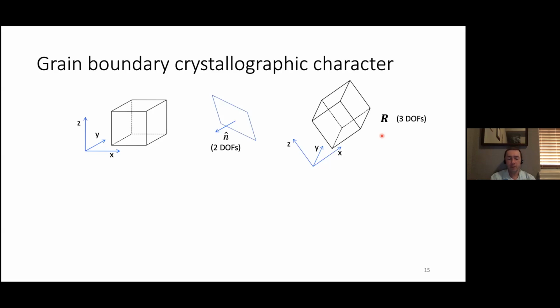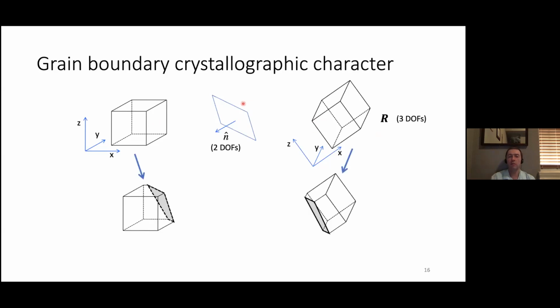Just to finish the thought here, once you have this grain boundary plane orientation, once you have the orientation of the two grains, what you do next is then you imagine cutting each one of those two grains along the boundary plane facet direction. Right, so imagine that I take this plane, I use it to cut this grain, I then cut this grain with the same plane orientation. You get these sort of facets that form, and then you can join those two grains and you get a grain boundary. Okay, so this is how we think about describing the crystallography of grain boundaries.